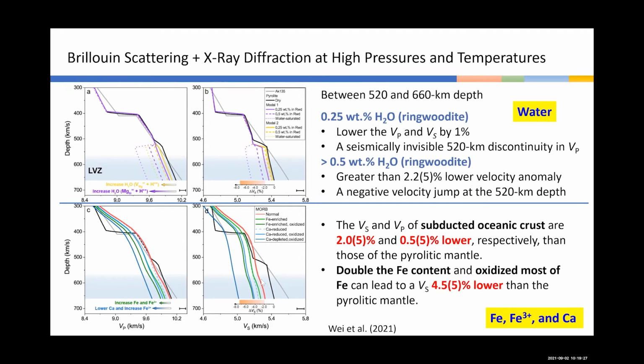For both Vp and Vs at the bottom of the transition zone, that is below 520 kilometer depth, we see that both Vp and Vs of the subducted oceanic crust are actually slower than the pyrolitic mantle, especially for Vs. Vs of the subducted oceanic crust is 2% lower than the pyrolitic mantle. So how about if we change the composition? If we double the iron content, and if we also oxidize the iron, changing the ferrous iron into ferric iron, as Kiseeva et al. reported in 2019 in Nature Geoscience.